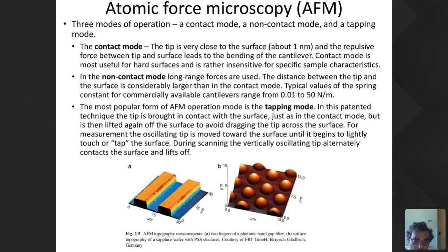In the non-contact mode, long-range forces are used. That means the distance between the tip and the surface is considerably larger than in contact mode. Typical values of spring constant for commercially available cantilevers are 0.01 to 50 N/m. The most popular operation mode is tapping mode. In this patented technique, the tip is brought in contact with the surface, just as in the contact mode, but is then lifted. First you have a contact, then the lift again off the surface to avoid digging or dragging the tip across the surface.